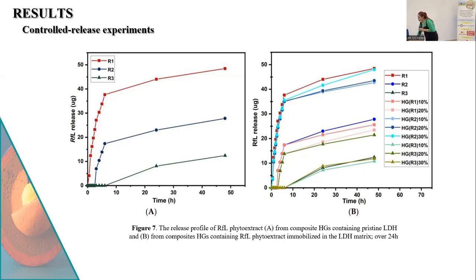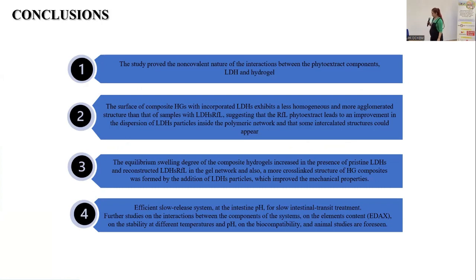So we can also observe that with the increase of the LDH inside the hydrogels, there is a decrease in the phytoextract release. But we can also observe that the release of the phytoextract depends very much on the type of LDH used. So in conclusion, this study proved the non-covalent nature of the interaction between the phytoextract components, LDH and the hydrogel. The surface of the composite hydrogel with incorporated LDH exhibits a less homogeneous and more agglomerated structure than the sample with the phytoextract.